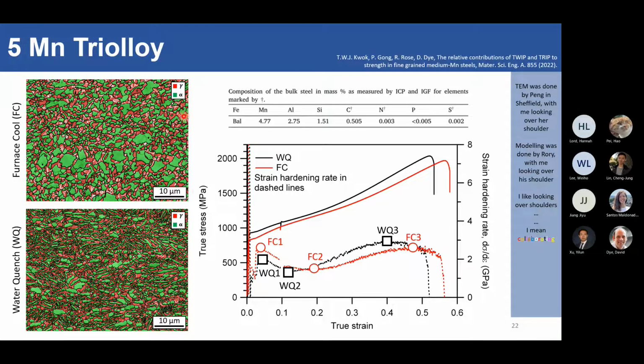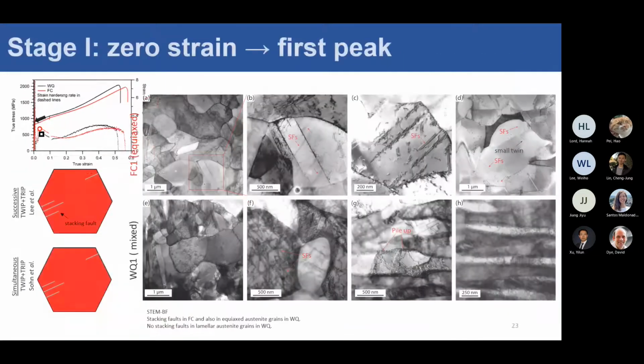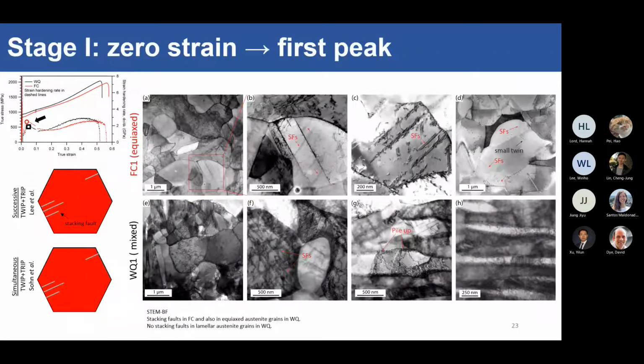But as you can see, they actually deform in the same way. So what's going on? They can't possibly be deforming the same way, right? So what we did was some interrupted tensile testing again, and then we took a look at the first peak, the saddle point, and then the second peak again to find out what's really going on in the microstructure to explain the tensile behavior. So if you look at the first peak, you can see in the FC sample, what you have is that you have a lot of stacking faults forming in the austenite grains.